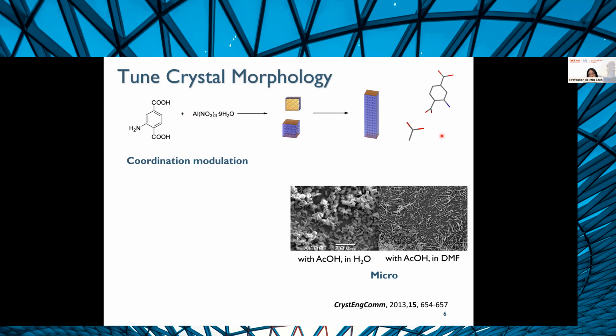However, if you throw in acetic acid into the mix, what ends up happening is that this acetic acid starts to compete with the carboxylate groups of the aminoterephthalic linker. And it selectively binds to these purple facets you see here.